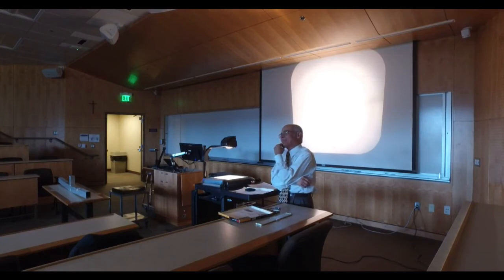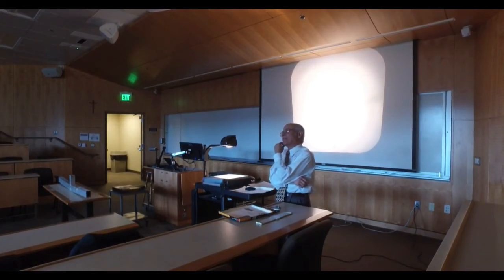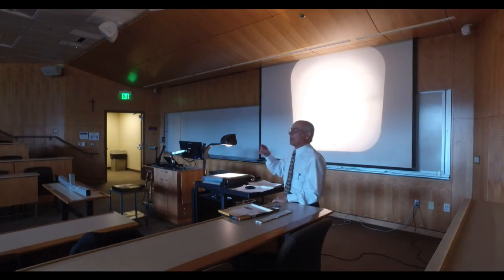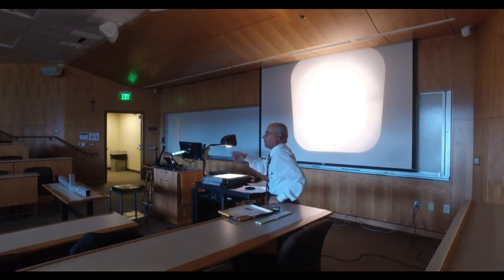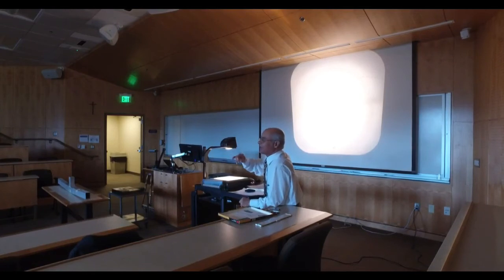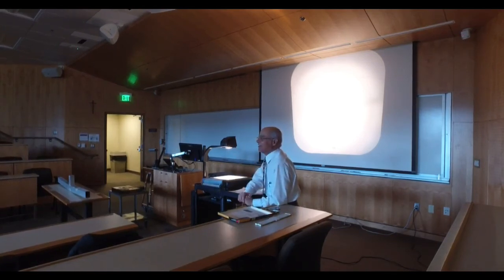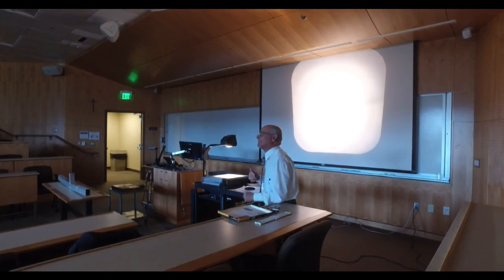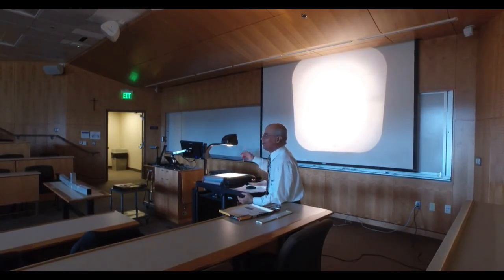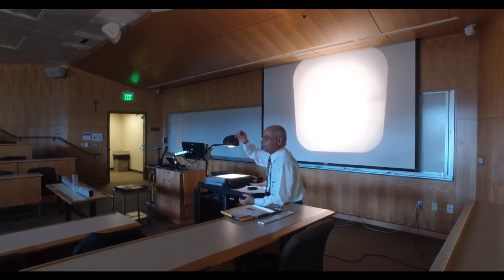Funny that you mention it, because while I was at OGI, we were involved in a project. In fact, we had a paper or two on that, vibratory stress relief, VSR. You may think that it's voodoo, and it may be voodoo, but I think there is something to it. Because what is happening, the idea is that as you are welding, or even after welding, you can actually vibrate. And I think what is happening is there's some micro plasticity going on, micro yielding going on, which is bringing the stress level slightly down. It's not going down to zero or anything like that. So yeah, it's voodoo science. In fact, residual stress analysis is also voodoo science. Although what you see there is a standard ASTM technique now for measuring residual stresses, but a lot of it is black art right now.